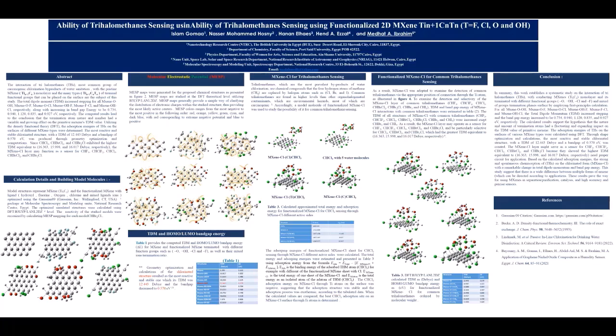The computed result led to the conclusion that the termination atom's nature and number had a variable and growing effect on the primitive MXene total dipole value. Utilizing density functional theory (DFT), the adsorption energy of trihalomethanes on the surface of different MXene types was determined.